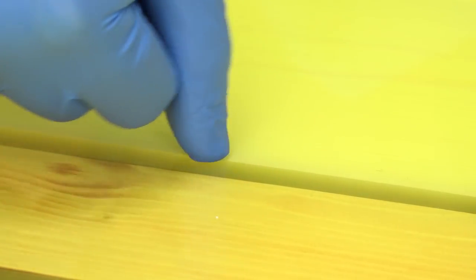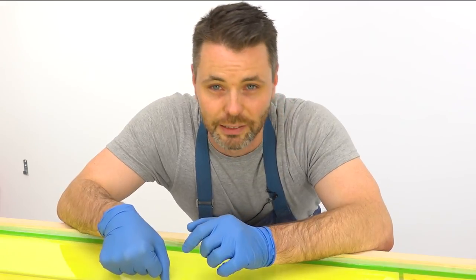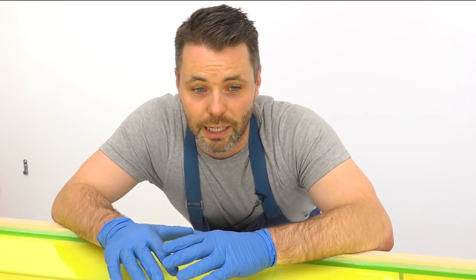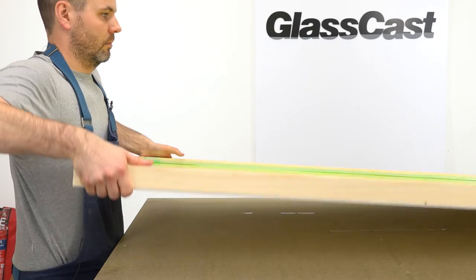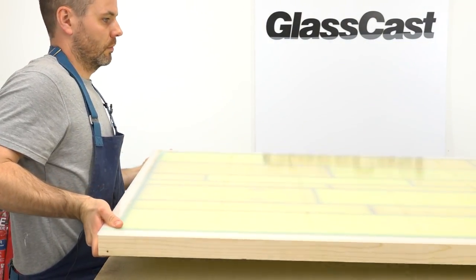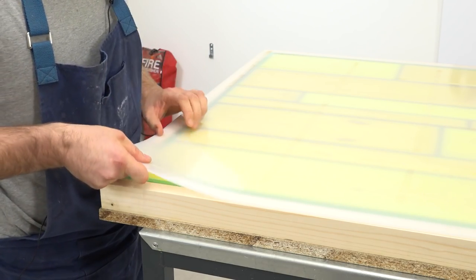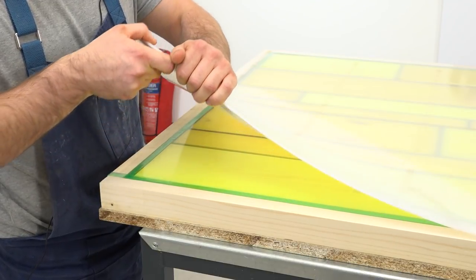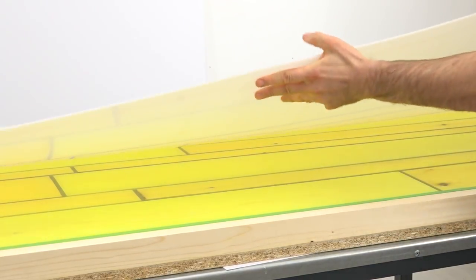You'll know that the resin's fully cured when it's impossible to leave a mark in the surface, no matter how hard you press down with your fingernail. That's where we're at, so we know it's now safe to handle, we can remove the barriers and get on with finishing the table. With the top turned over, it's easy to separate from the baseboard, and you can see that we've got a really good finish on the underside of the table.